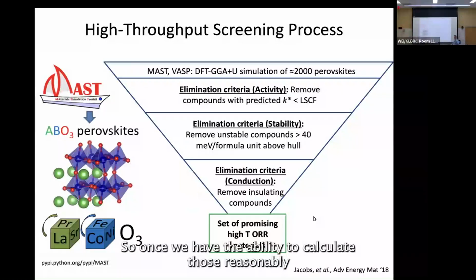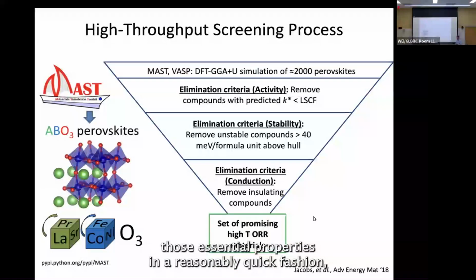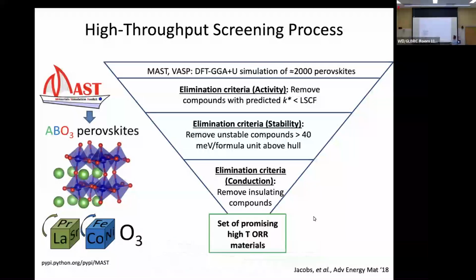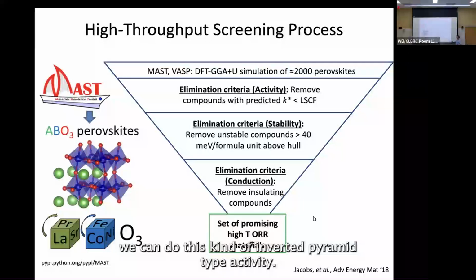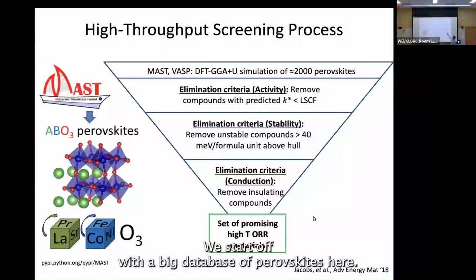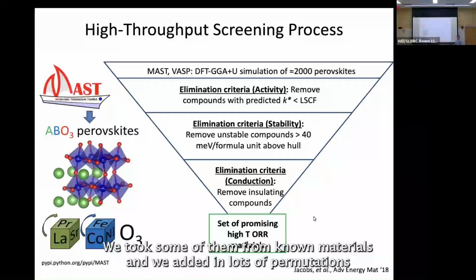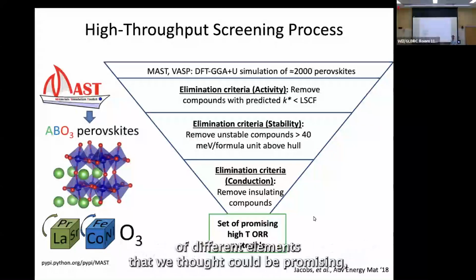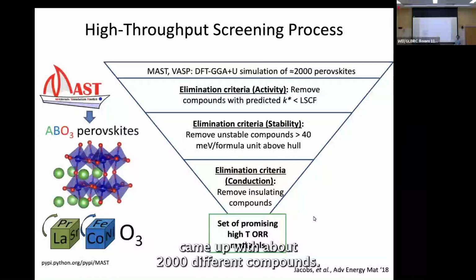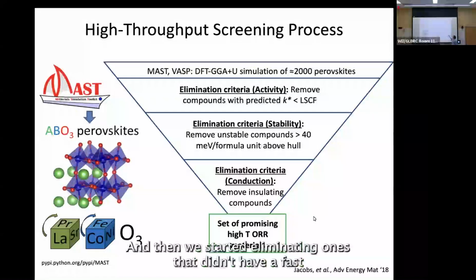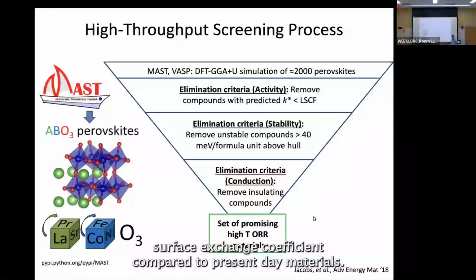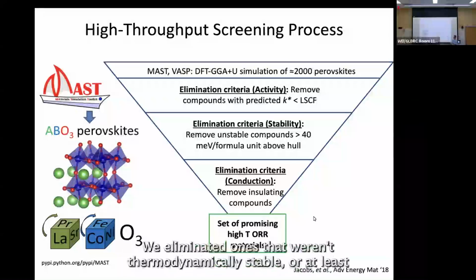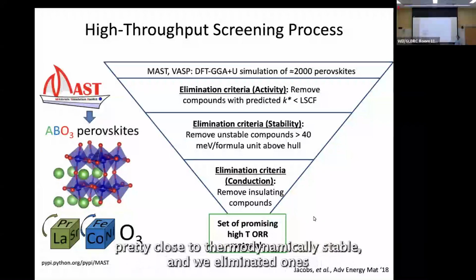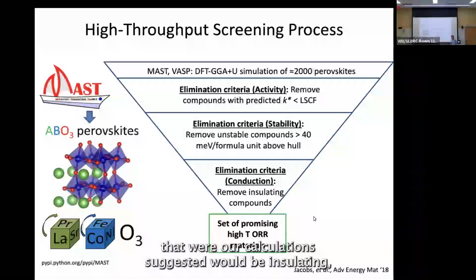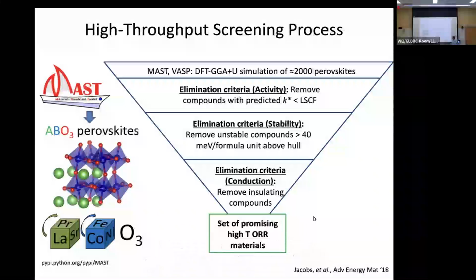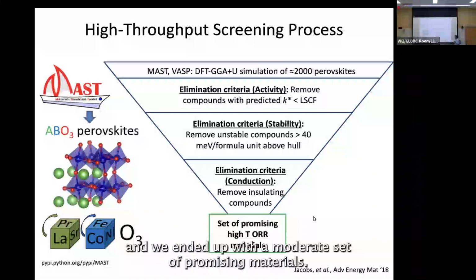So once we have the ability to calculate those essential properties in a reasonably quick fashion, we can do this kind of inverted pyramid type activity. We start off with a big database of perovskites. Here we took some of them from known materials and we added in lots of permutations of different elements that we thought could be promising. Came up with about 2,000 different compounds. And then we started eliminating ones that didn't have a fast surface exchange coefficient compared to present day materials. We eliminated ones that weren't thermodynamically stable, or at least pretty close to thermodynamically stable. And we eliminated ones that our calculations suggested would be insulating. And we ended up with a moderate set of promising materials.